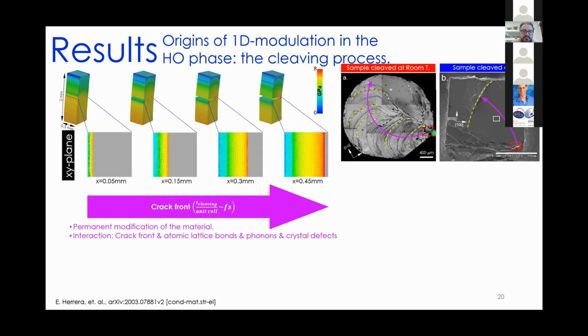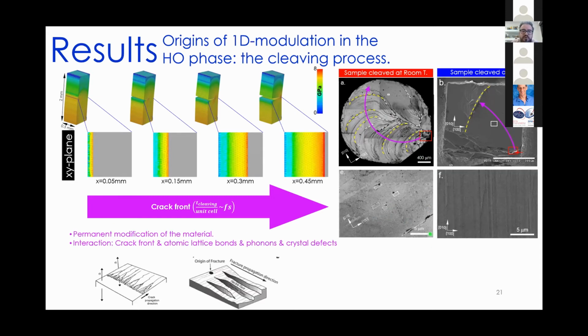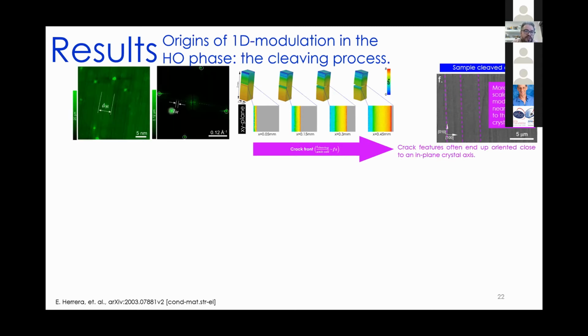This sample was cleaved at room temperature, and this sample was cleaved at lower temperature. I'm not going to go into details, but what I want to remark is that when we measure regions of around some microns, the main difference is that on the sample cleaved at low temperature we have a set of linear features created during the fracture. They are oriented closely to a crystalline axis, nearly parallel to the atomic lattice, as I represent here with these purple lines. Let me remind you that from our experimental results, the modulation that we observe is also nearly parallel to the in-plane crystalline axis.